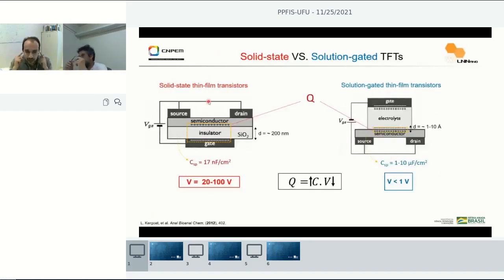And so we can imagine that if you compare the two architectures, solid-state thin-film transistors and solution-gated thin-film transistors, to induce the very same amount of charge in the channel, there are important implications if you use a thin film insulator or an electrolyte. By using solution-gated transistors, where the capacitance is orders of magnitude higher than in a solid-state analog, to induce the same amount of charge we use much less voltage.